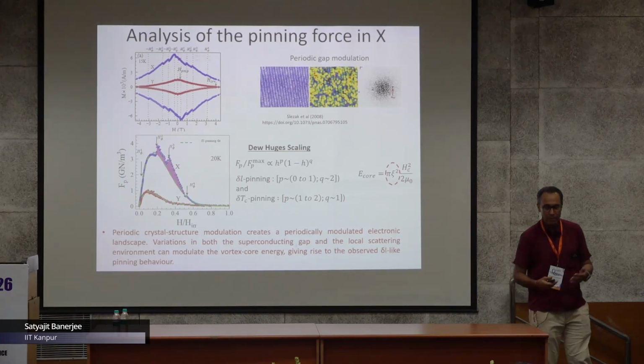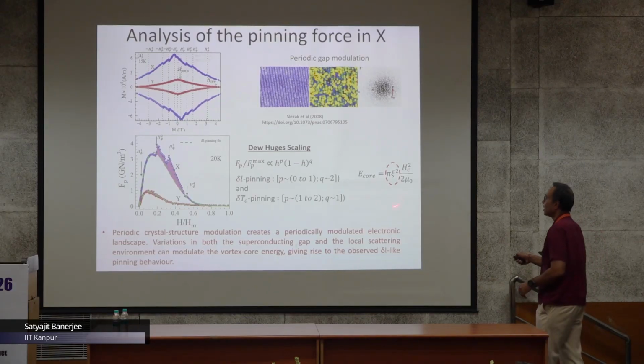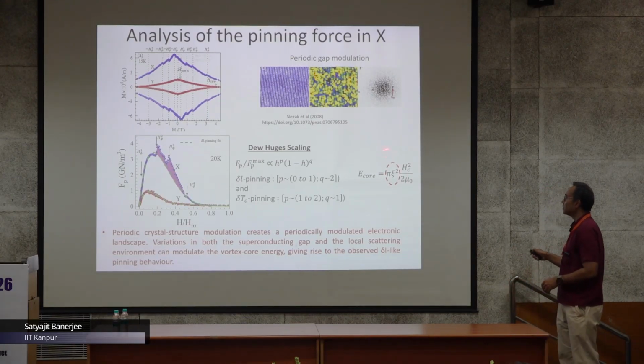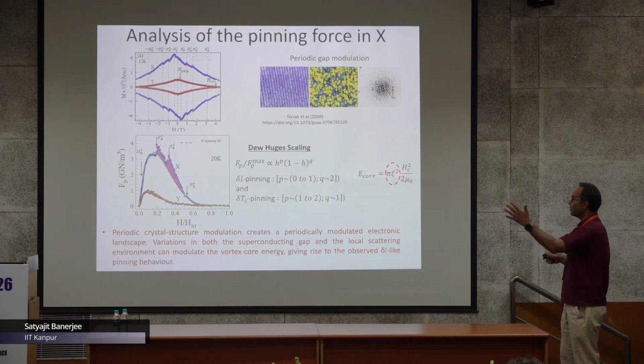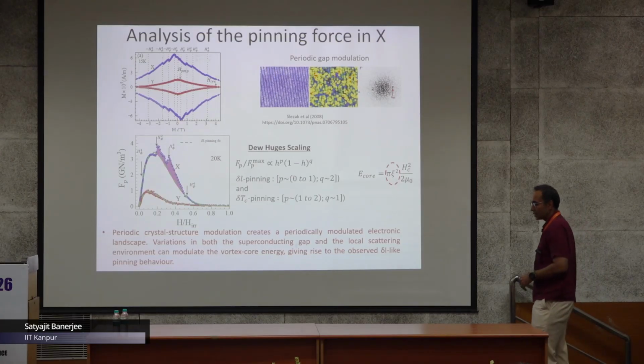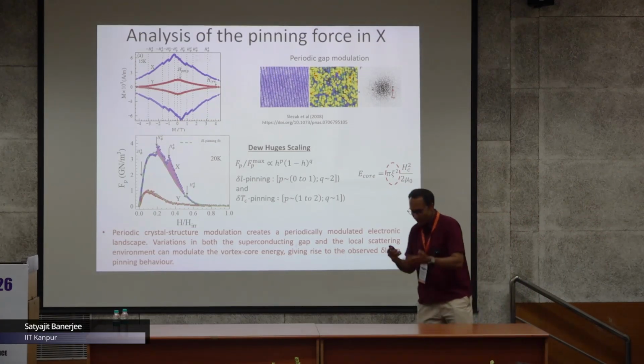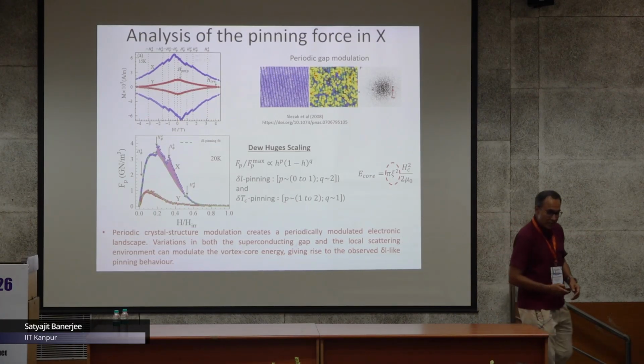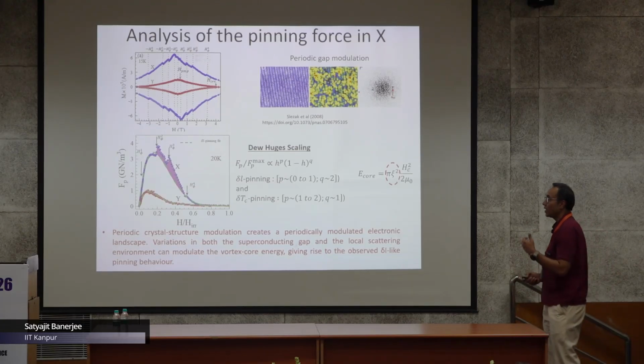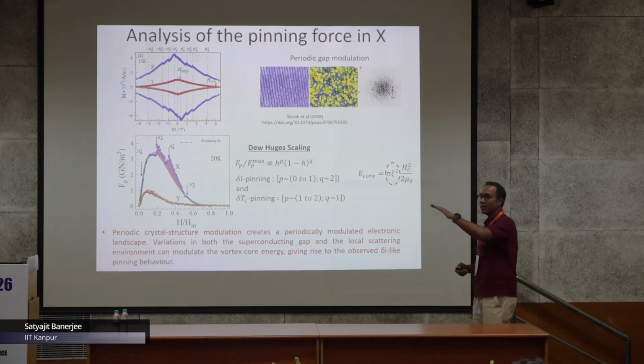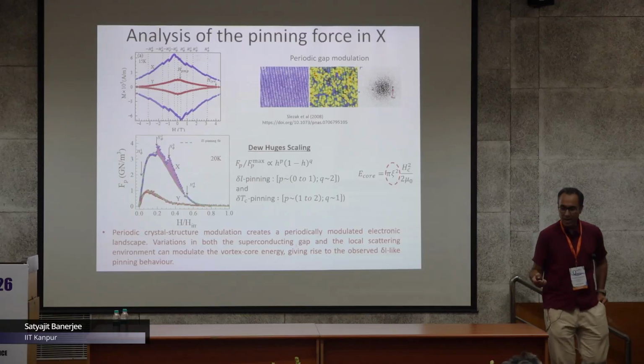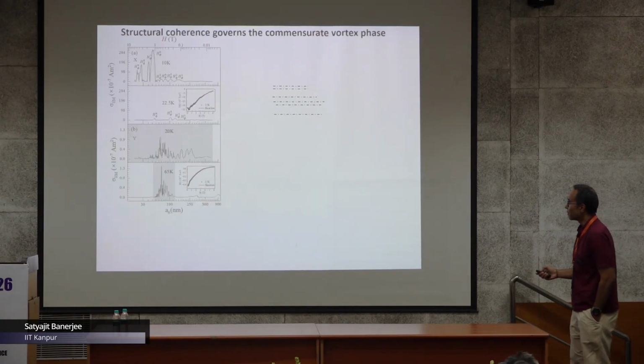We believe both may be happening, because the vortex core has contributions from variations in the mean free path as well as the condensation energy, which can also vary. Both of these, I think, participate and play an important role in creating these intrinsic modulated states and causing pinning inside the crystal.